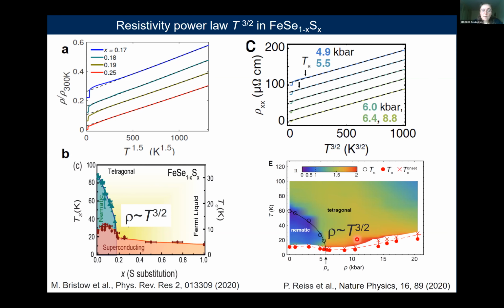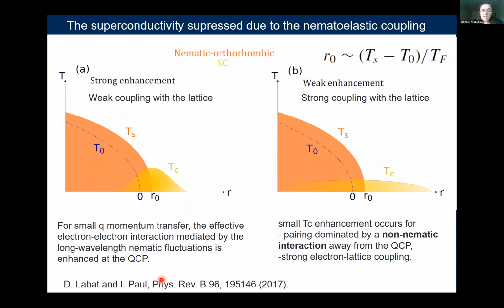Also, in both cases, you can see that the superconductivity is not enhanced. It's clear something significantly affects this critical fluctuation because they are strongly suppressed. And this, again, has been discussed in a recent paper by Labat and Paul, that in the presence of a weak coupling with elasticity, one expects the nematic fluctuation to be enhanced and to have a domal superconductivity in the vicinity of the nematic critical point. But when this coupling is strong, that enhancement is suppressed, and also we might expect the pairing to be dominated by non-nematic interactions.